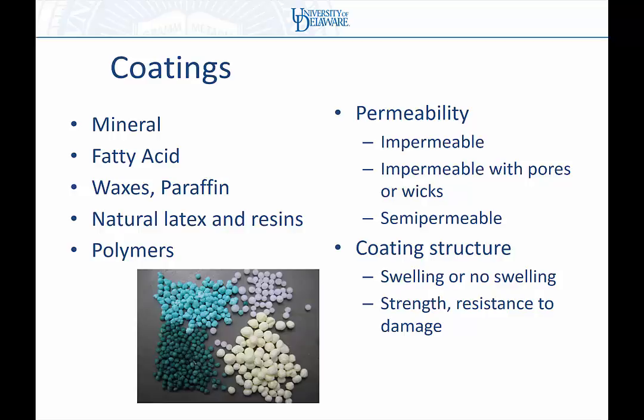It has to be somewhat impermeable, but it can't be totally impermeable because then the fertilizer inside would never dissolve. So what they have done technology-wise is they've either taken an impermeable coating and added additives to add wicks or pores so that it can allow some water in, or they produce a semi-permeable material like a membrane that has pores that allow water in and diffusion out, but it still maintains the integrity or shape of the coating.